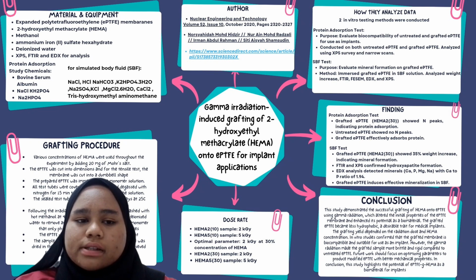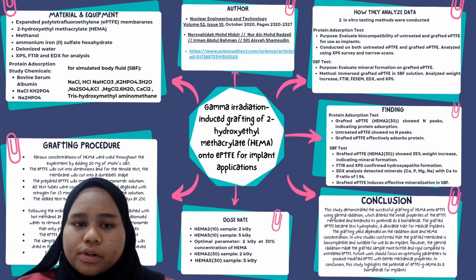The conclusion of the study is to demonstrate the successful grafting of HEMA onto ePTFE using gamma radiation, which altered the initial properties of the ePTFE membrane and enhanced its potential as a biomaterial. The grafted ePTFE became less hydrophobic, a desirable trait for medical implants. The grafting yields depend on the radiation dose and HEMA concentration. So in vitro studies also confirm that the grafted membrane is biocompatible and suitable for use as an implant.